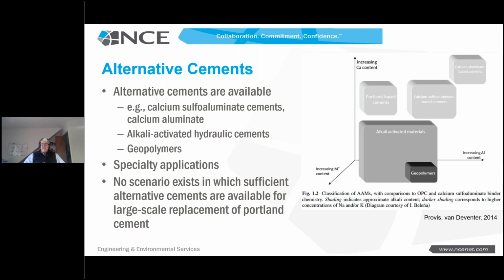So these are available. Runways have been built with geopolymers. Alkali activated hydraulic cements are on the market as some high-end specialty materials. Calcium sulfoaluminate cements are commonly used as a very good rapid set repair material. But there is no scenario in which a sufficient amount of alternative cementitious materials exists to replace the versatility and the availability of Portland cement. So we can nibble around the edges and make some inroads, but we're not likely to solve our problem this way.